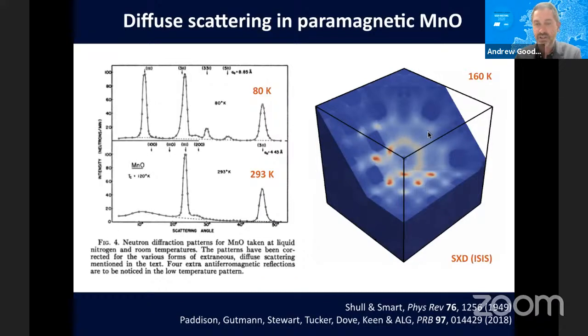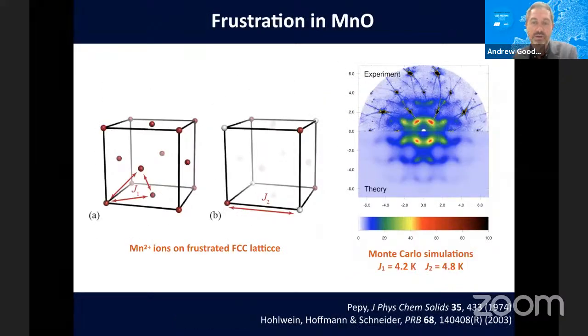And in fact, here is some data from Matthias Gutmann, now single crystal data. These broad blobs that you see are just the smear that you see in the powder diffraction pattern. And this is characteristic of the existence of non-trivial magnetic structure in paramagnetic MnO. So that's what I mean by correlated disorder and the fact that it has some signature in scattering patterns. Let me just turn quickly to how you might go about analyzing it. There are lots of different ways of doing that. I thought I'd just use MnO as a very simple introductory case for this.